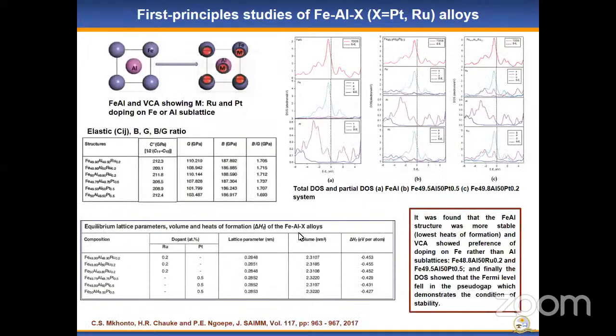Now, some of the results here: you can see this work was done on iron aluminum by Mr. Mkhonto here, and the work was published back in 2017. So also from the results of VCA, you are able to use the same principles of looking at the heats of formation and the densities of states, then you compare them and see how you can rank these systems. So here we're looking mainly at ternary systems, which are a bit high, but importantly, with the VCA you can run calculations in very minimal time as compared to when you're using the supercell approach. So those are the differences between the supercell approach and the VCA approach.